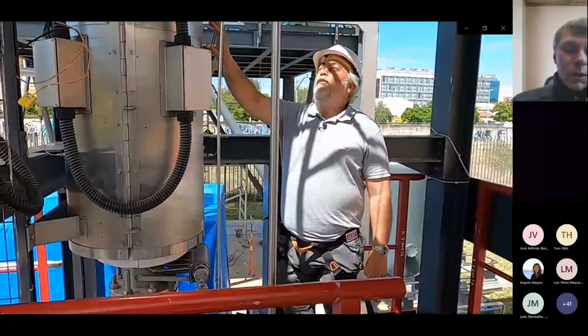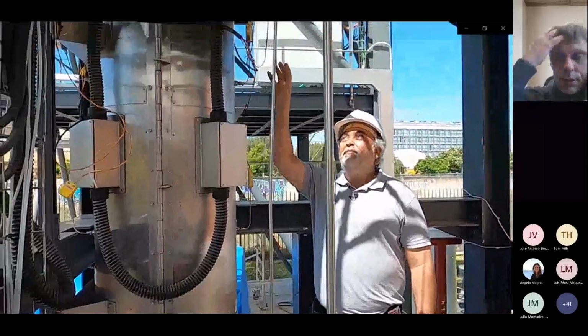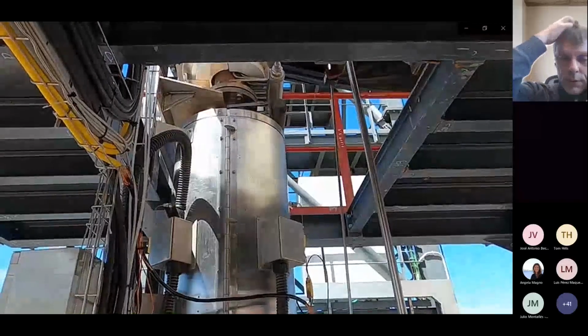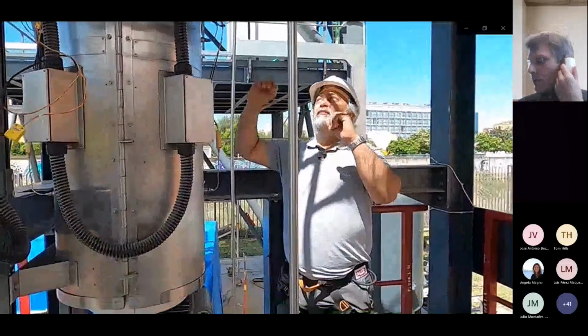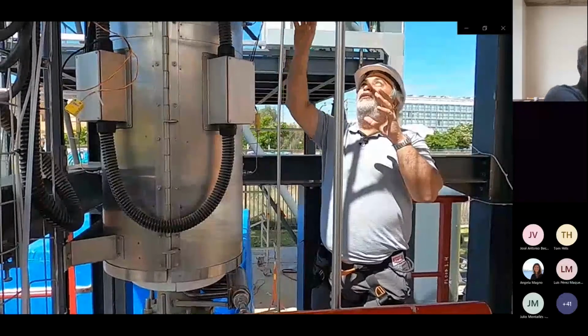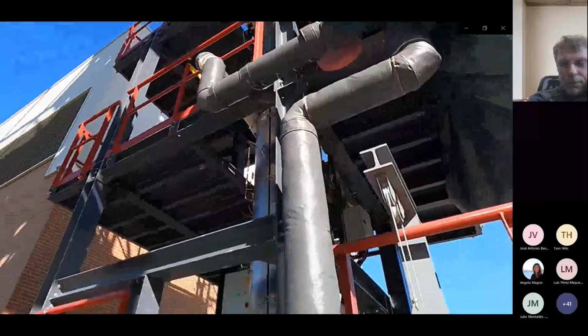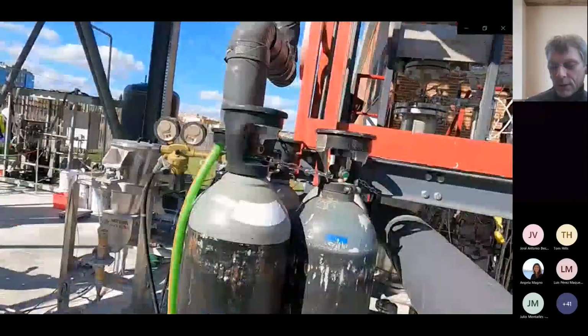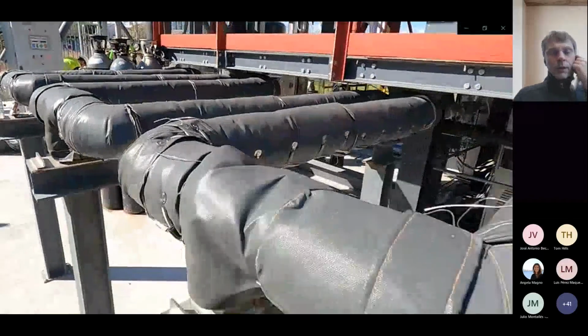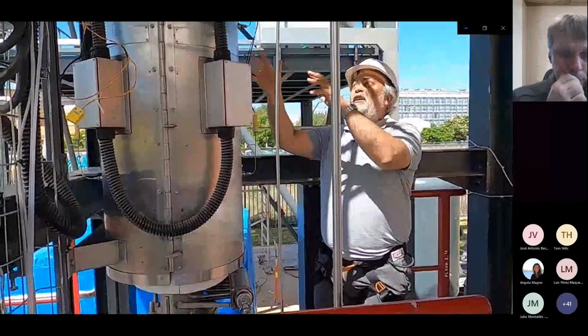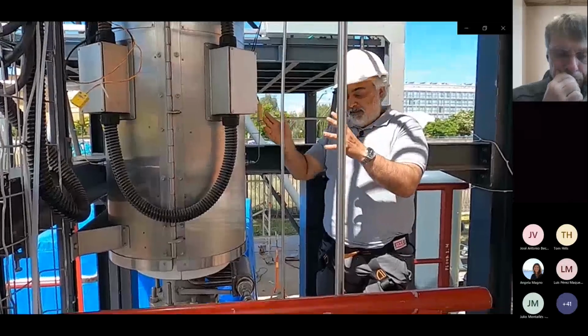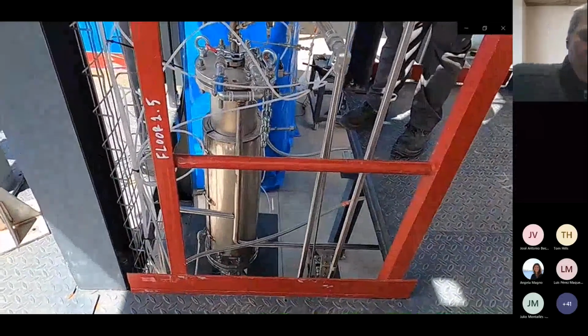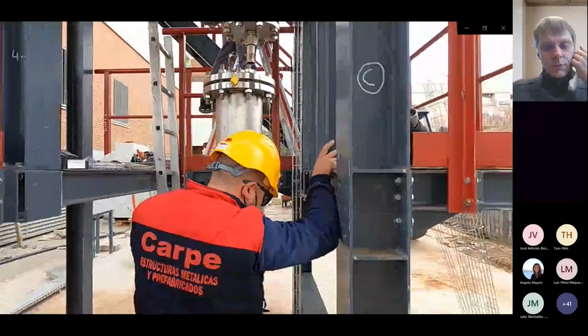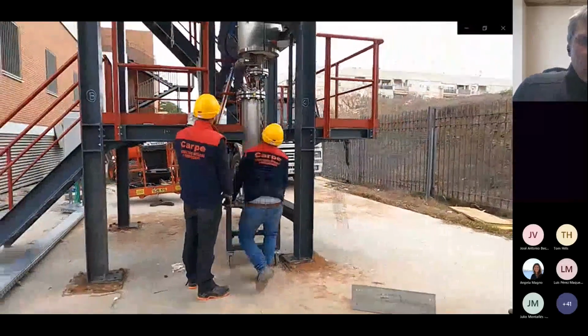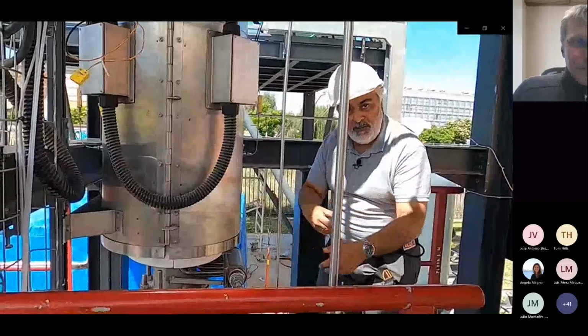Here the calcium oxide, previously supplied by the screw feeder, is mixed along with the CO2 stream in a reaction that releases energy. This thermal energy is collected by a bundle of tubes, which conveys to the stream of compressed air, heating the air and delivering the thermal energy to the Stirling engine in the power block. The result of the reaction, which is again calcium carbonate, is collected in this lower vessel, which later will be moved to the screw feeder for the calciner tower, closing the cycle.